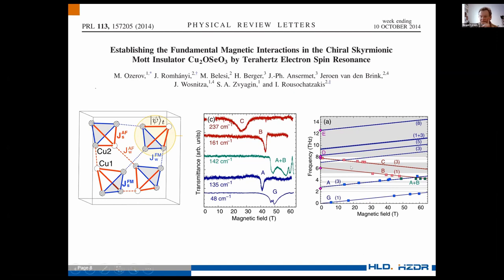And this is frequency and field dependent. This gray area is phonons. This is where the sample is not transparent. That is why you need tunability or a multi-frequency approach, just to avoid hitting phonons. Otherwise, you don't see anything. If you are heating phonons, your temperature sharply increases. Instead of 2K, for instance, you might end up with 10K quite easily, but by slightly changing the frequency, the temperature goes back to 3K and you can actually measure the excitation spectrum.